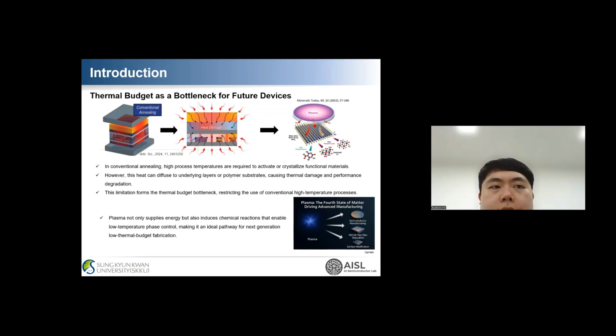Plasma provides a non-thermal energy source that not only delivers energy, but also induces surface reaction, generates oxygen vacancies, and promotes local structural changes. In other words, plasma enables crystallization and localized phase transformation without increasing the overall substrate temperature. For these reasons, we consider plasma to be highly suitable for low temperature processing.